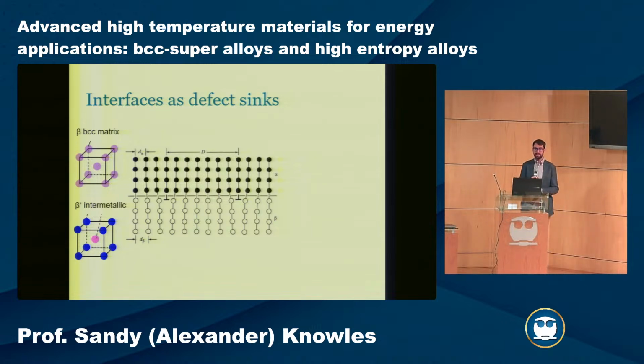What we really wanted to look at is chasing this idea of using interfaces as defect sinks. If you have an excess of vacancies or dislocations within the material, and you have a large number of interfaces, all of those interfaces can act as sinks for radiation defects. If you imagine this is a dislocation at the interface, if a vacancy moves to that region, it can just extend the dislocation line, and you allow for the annihilation of that vacancy. If you can reduce this accumulation of defects within the material, you can make it more resilient to radiation damage. And the nice thing about these materials is that we have this method for understanding the phase diagram to tune the microstructure and design nanostructures with a very high interface density.